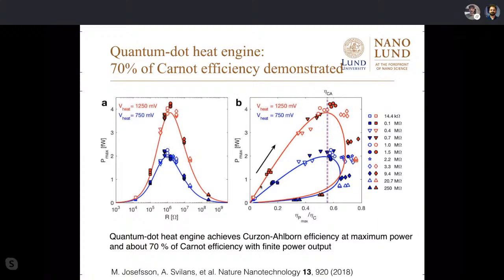So this is for two different heat settings. Let's look at the red one first. That's the higher temperature difference. For each setting of load resistance, we can extract, in multiple experiments, power and efficiency, and find that there are load resistances that give us higher power and there are load resistances that give us higher efficiency. And these follow quite nicely a loop graph where the line again is the theory prediction and the dots are experiment. We also marked where the expected Curzon-Ahlborn efficiency is for the system and find that the maximum power is very nicely reproduced at the expected value of Curzon-Ahlborn efficiency of a bit more than 50%. And depending a little bit on how you choose to see this, we can extract efficiencies above 70% of Carnot efficiency.